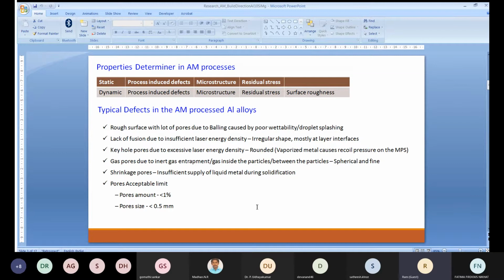So if you find irregular shaped porosities, then it is lack of fusion. Second is if you use excessive laser energy density. As I said earlier, some elements in the molten pool will get vaporized. This vaporized metal causes a recoil back pressure on the molten pool surface, causing keyhole porosities. This looks like a rounded shape. Third is the gaseous elements like oxygen, nitrogen, hydrogen causing gas porosities. It is mainly due to gas entrapment in the molten pool.